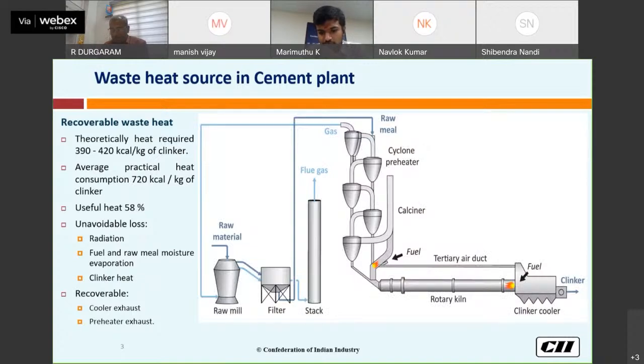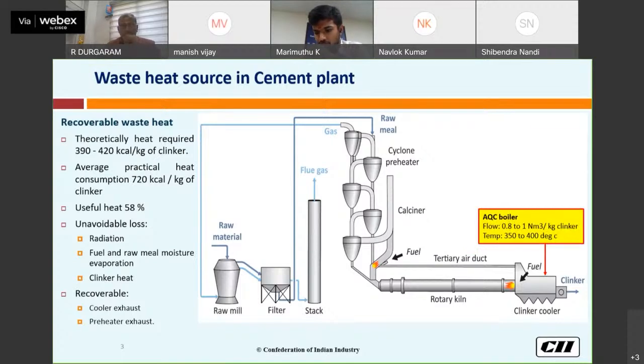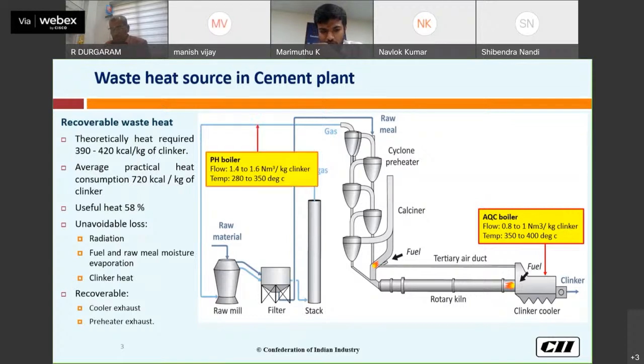So this is the simple process diagram of the clinker cooler and preheater stages. On the right side, you can see the AQC boiler is normally designed for a flow of 0.8 to 1 Nm cube per kg clinker. There we will have heat at a temperature of 350 to 400 degrees centigrade. In the case of the PH boiler, we have a flow of 1.4 to 1.6 Nm cube, and there the temperature is around 280 to 350 degrees.